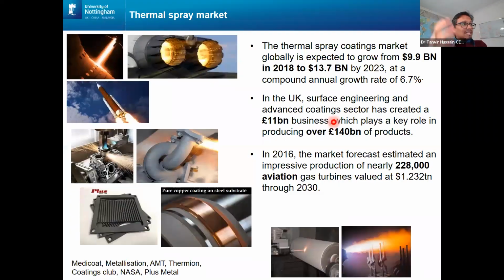The coatings market, specifically the thermal spray coating market globally, is expected to go from around 9 billion to 13.7 billion by 2023, a compound rate of 6.7%. Examples of coatings: the afterburner, gas turbines, space rockets, and also your automotive engines are coated. The exhaust manifolds are also coated. We also have cold spray coatings, on copper-based systems, which don't oxidize when you're depositing because it's a cold system, and also making net shape manufacturing components like this. This is a paper roller. The paper roller industry needs a very hard wear-resistant coating for paper and printing application.